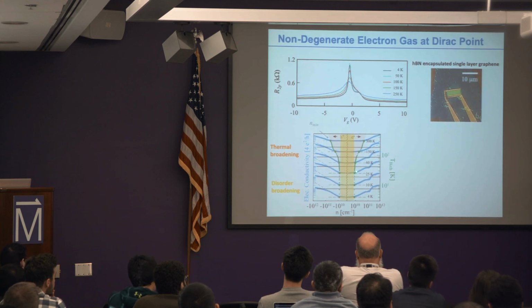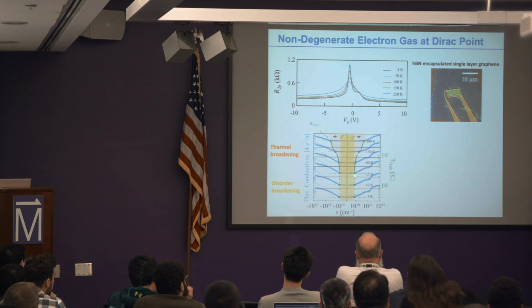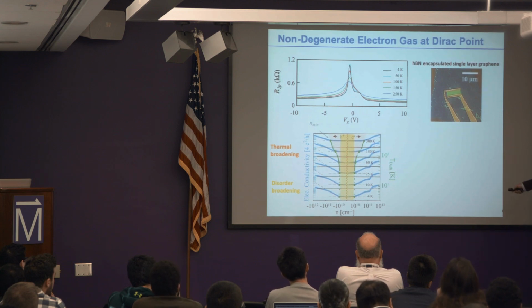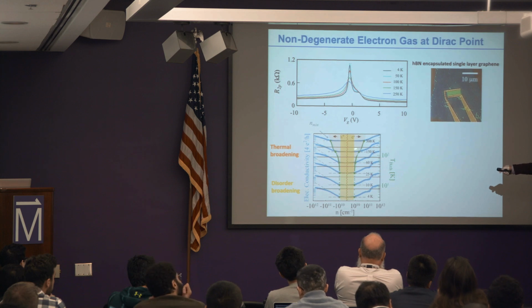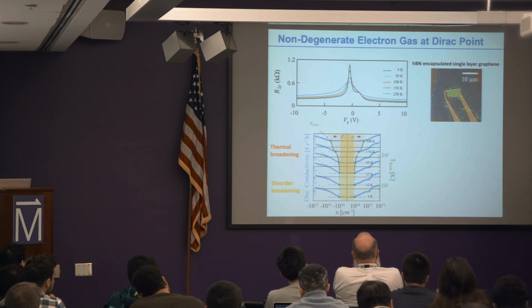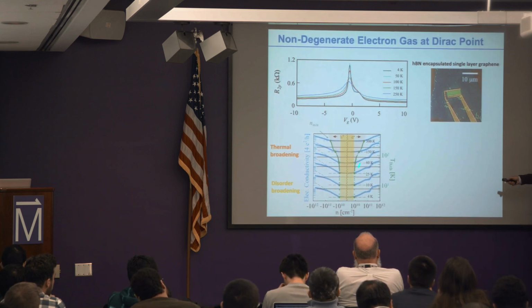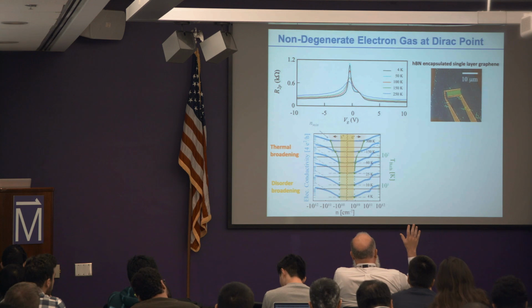In this particular sample, below about 25 Kelvin you are still limited by disorder created by residual electron puddles. But above 25 Kelvin, you start to see the effect of thermally populated electrons and holes in the system. More likely you are moving toward the Dirac fluid region above 25 Kelvin. So that's what you're seeing.